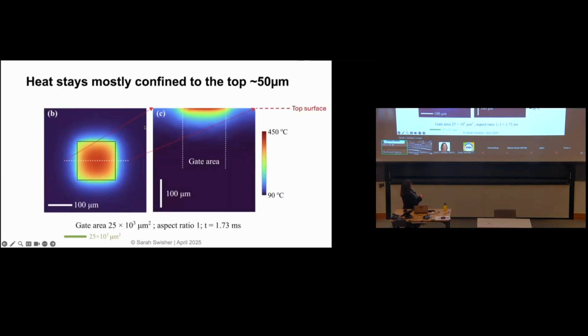So what we see is with this 3-dimensional model, we can show the non-uniformity across the gate. So notice we've got a hot spot in the middle. A 1-dimensional model doesn't show you that. A 1D model tells you that everything here is the same temperature, which is not true. So when you design your device, you need to know where to put that channel. The other thing that we can see is the heat as it goes down through the substrate this way. And we can look at this as a function of these different areas and aspect ratios.